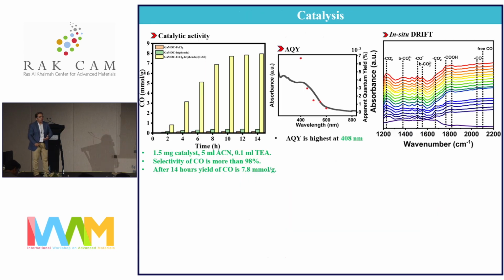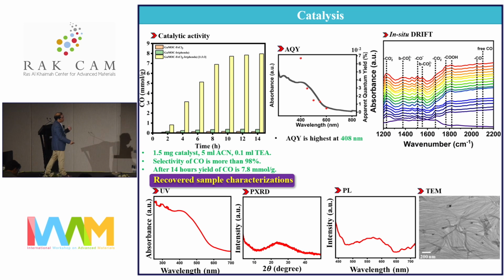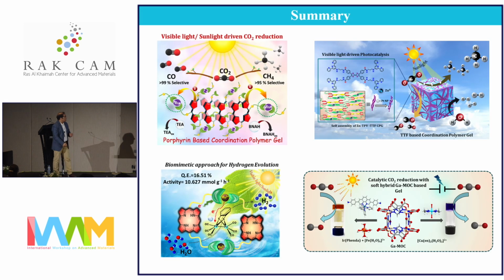You can study the photocatalytic activity, which I performed, and we got CO production here, which you'll track. So lastly, what I've shown is that soft materials can be used for photocatalytic applications, where covalent integration of the light-harvesting moiety and catalytic sites is very important, because the electron transfer pathway will be shorter and faster, and you can tune the product by changing the sacrificial agent.